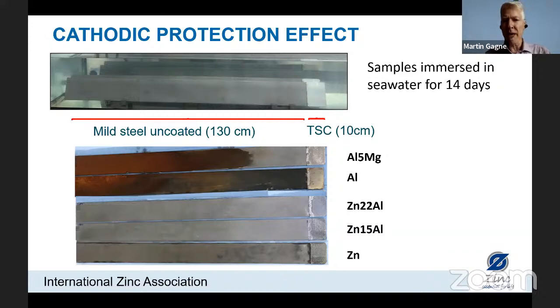So the aluminum alloys, there's a 5% magnesium alloy. There's also a pure thermal spray aluminum. So we can see on the right-hand side the small 10 centimeters of steel that was coated, but the exposed steel is showing significant red rust here.